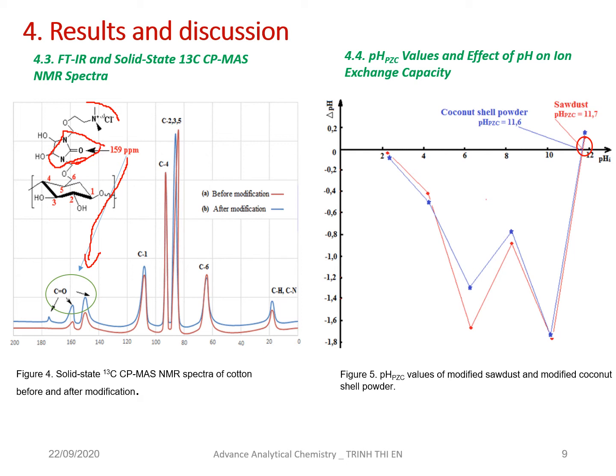This ammonia source is created, and then the author measured the pH at point of zero charge by the graph, with the delta pH as the result, and this determined the pHPZC value: for sawdust it is 11.7, and for coconut shell it is 11.6.